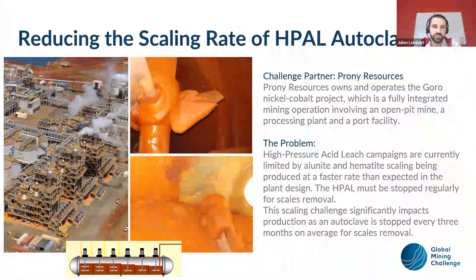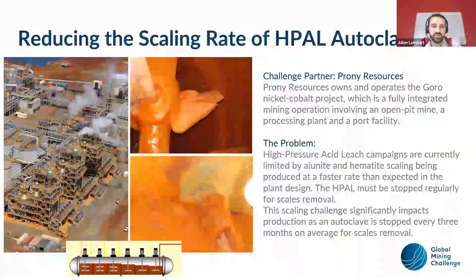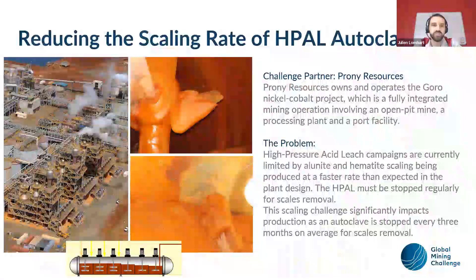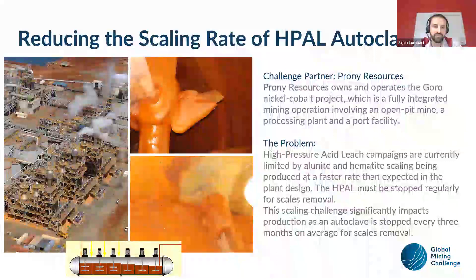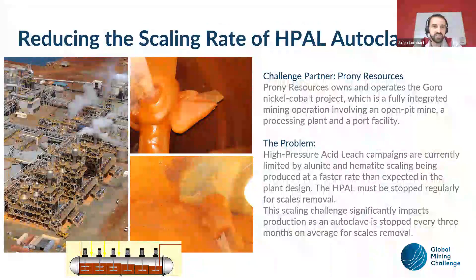We now need to find solutions to reduce this scaling rate, which is very important, or to be able to measure the thickness of the scales. We have to stop the autoclave after a certain number of days of operation without knowing the exact thickness of the scale, but from experience we know that after 120 to 140 days of operation we see a significant decrease in autoclave efficiency due to scaling.